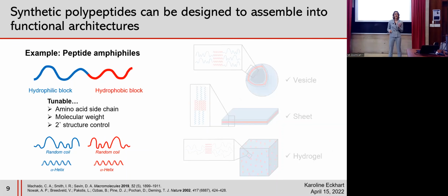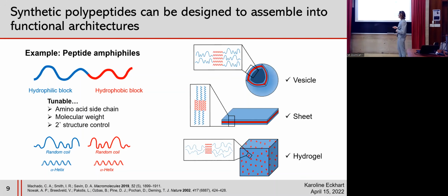Peptide amphiphiles are a key example of how we can use NCA-ROP to make a functional polypeptide. A peptide amphiphile is essentially a block copolypeptide that features a discrete hydrophilic domain and a discrete hydrophobic domain. And by controlling the amino acid side chain and the molecular weight of the respective blocks, we can access different secondary structures in the peptide amphiphile blocks. And these secondary structures result in tertiary structures and then quaternary structures so that these synthetic polypeptides can form useful biomaterials like vesicles, sheets, and hydrogels, which are interesting vehicles for drug delivery as well as 3D tissue culture and wound dressings.